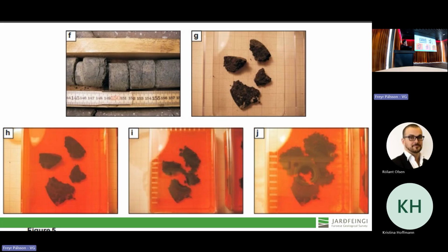What the ethylene glycol does differently than water is that the molecules are bigger and they will saturate the swelling. So it will foresee what will happen after many wetting and drying cycles with water. Ethylene glycol will speed up the process.